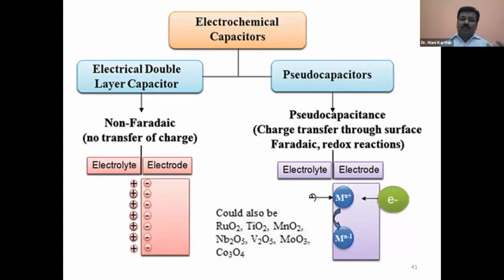So maximum, as per the state of the art, if you use EDLC with organic electrolytes, you can go for 100 or a maximum of 150 farads per gram. You cannot increase it because it is already saturated. I will explain the carbon behavior also in the following slides. If you see the pseudocapacitor, people are even going for 600, 700 farads per gram of the active material, but it depends on the active material.